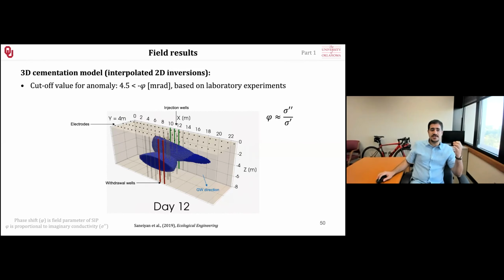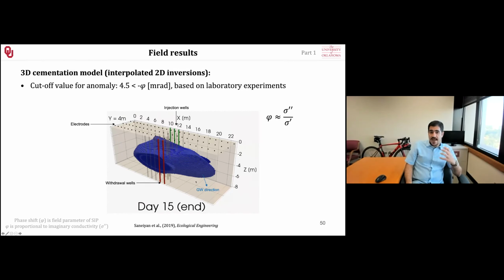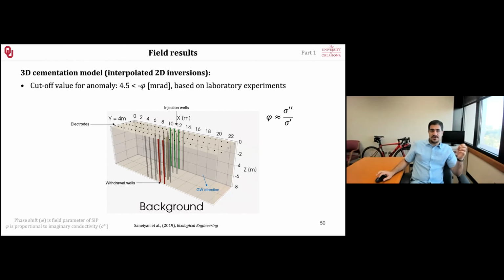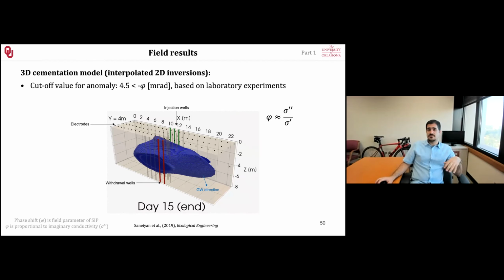And as you can clearly see here, we are also seeing more precipitation in the direction of the groundwater flow. So our geophysical technique is much more effective at mapping the subsurface affected by MICP than direct sampling, such as shear wave velocity, I would say, and a lot of other methods. All you need in future is just a small amount of measurement showing that the MICP actually worked. That could be an effluent sample or something, and the rest is by geophysics. You can install these electrodes permanently on the site, do your measurement, and basically enjoy.